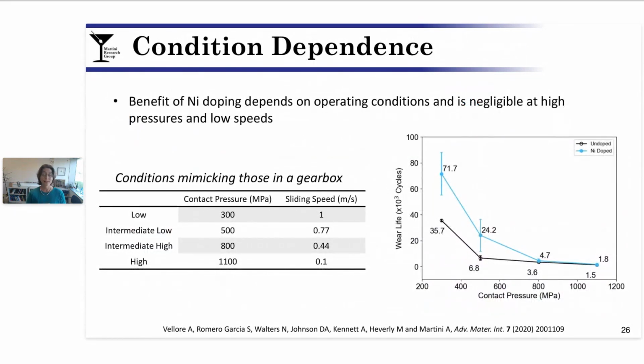However, we repeated this same test at different operating conditions. Specifically, we performed the test at different pressure and speed conditions designed to mimic those that would be expected in a corresponding gearbox for a space application. The results are shown here on the right, where you're looking at wear life as a function of pressure, where again, the speed is also varying. And the main take home here is that at low pressures and high speeds, indeed the nickel is beneficial and helps extend the wear life. Whereas at high pressures and low speeds, we see really no benefit from using the dopant in these cases.